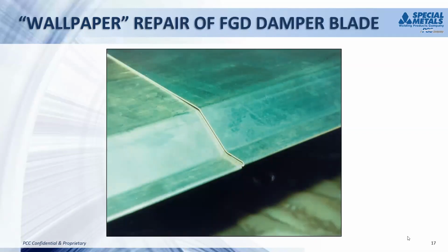The next slide shows that cladding is not the only thing that can be done with wallpaper. Here was a case where a damper blade had corroded and it either had to be replaced or repaired. The repair was accomplished by welding 1.6 millimeter sheet over top of the existing damper, again by the wallpaper technique. So that way, instead of replacing the damper, it could be repaired and put back into service quickly.